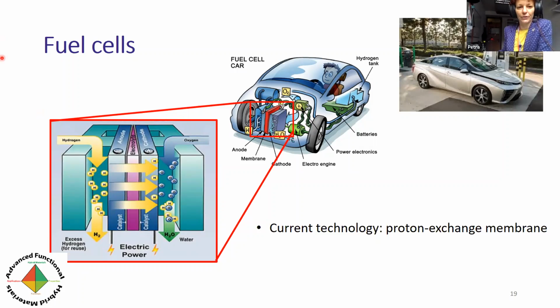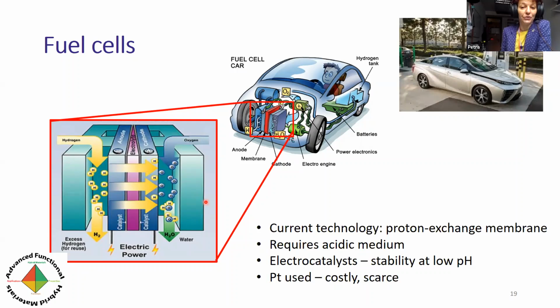Now, the issue is that we need a proton transport through this membrane, and that means that the pH will be very low. That means that this is a highly corrosive environment. So, of course, our electrodes and electrocatalysts need to be so robust as to survive in these highly acidic media, which means that in practice you need to use platinum, which is of course a very costly electrocatalyst, and it's becoming increasingly scarce as well.